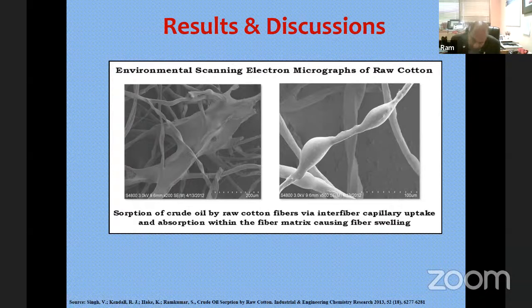more. While they are adsorbing more because of high surface area, these low micronaire or immature cottons are relatively porous compared to mature cotton, because in mature cotton you have more cellulose deposition. In immature cotton, the cellulose deposition is less. So not only is it adsorbing on the surface and spreading on the surface, it also goes into the individual fiber. That is very important.